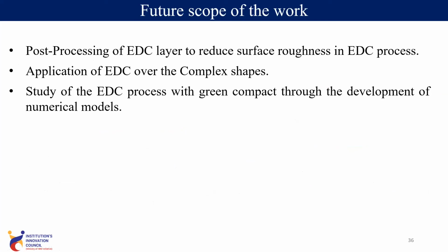Now, the future scope of the work: post processing of the EDC layer to reduce the surface roughness. Basically, the EDC process gives a large surface roughness which cannot be used in some industrial components, so post processing is required. Post processing can be done by performing the EDC process again on the obtained surface. Then, application of EDC over complex shapes. As we can change the shape of the green compact tool, if we use a complex shape tool, it is possible to coat a complex shape workpiece.